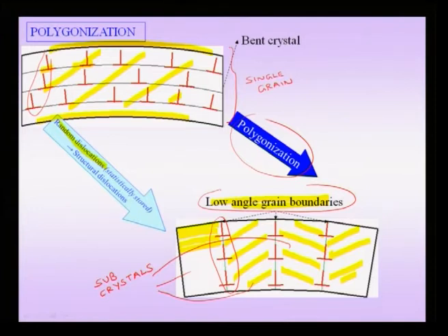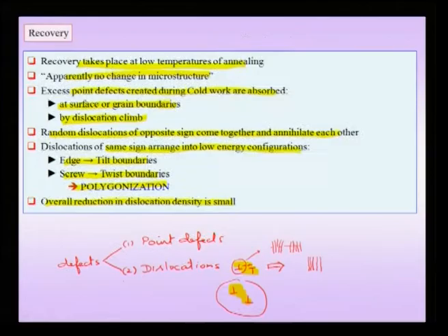So, let me summarize what takes place during recovery. During recovery, a material partly goes down to a lower energy state, but because the thermal activation is not very large, we have not heated it to a very high temperature, the major reduction is actually in the point defect density, which could include self interstitials and vacancies, and these vacancies for instance could be absorbed at surface or grain